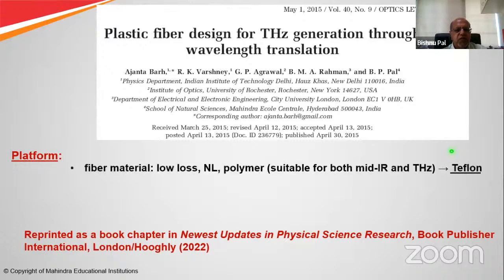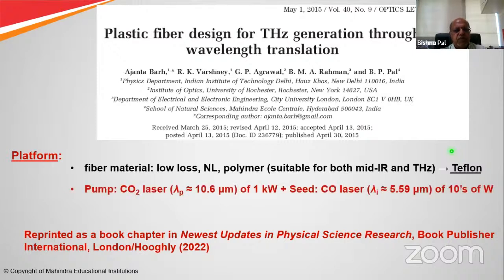The platform that we used was a nonlinear polymer, typically Teflon. This Teflon is a suitable polymer which has an n2 value, a nonlinear coefficient of its refractive index, and it is suitable for both mid-infrared and terahertz. In this case we assumed a CO2 laser, which you know is available. Kumar Patel was the discoverer of that when he was in Bell Lab. It emits at a wavelength of 10.6 micrometer and a power of 1 kilowatt, which sometimes makes people raise their eyebrows.